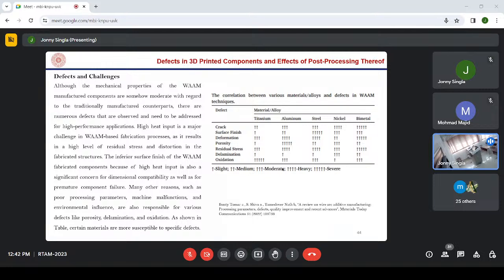Similarly, surface finish is severe, that means poor, in case of steel. And deformation is maximum in case of bimetal. Porosity is maximum in case of aluminium. And residual stress is maximum in bimetal. And delamination is also high in nickel, and oxidation is maximum in titanium. So these are the cracks, and this is how they appear in different materials.